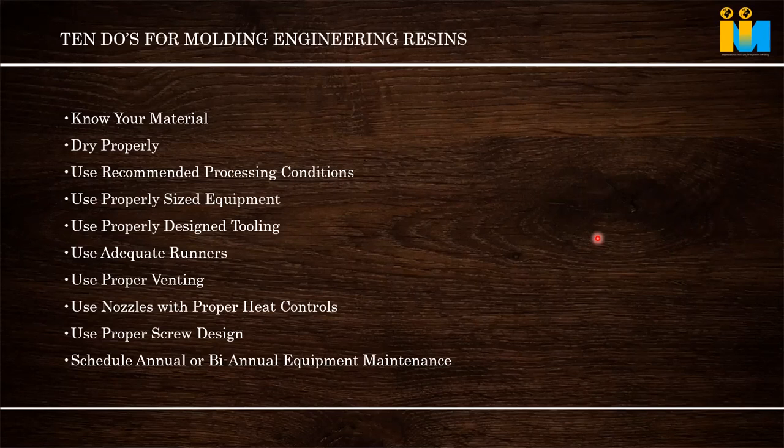For one material, polypropylene mixed with a highly loaded pigment, thick green color, it has to be mixed properly. So they use a high shear rate mixing screw. PP can take 1 lakh shear rate and it can be mixed. If you use the same screw for PC, it burns the PC. We cannot use that because PC is a tougher material. We cannot just over-compress, mix it heavily and mold it. Then it burns, and the molecular weight will be damaged. So based on the material we have to select the screw.